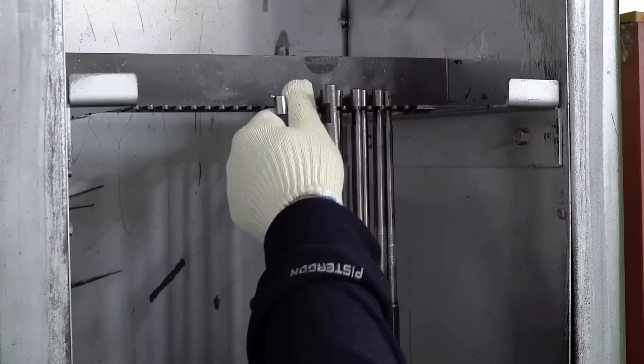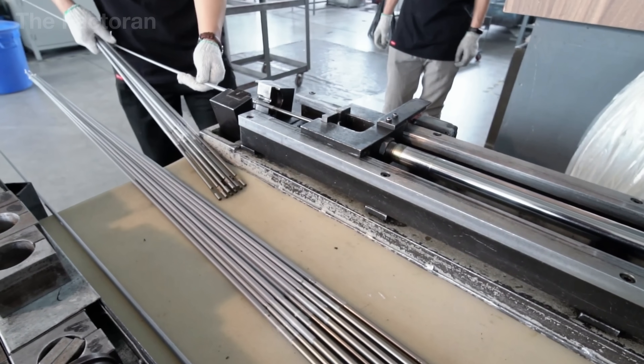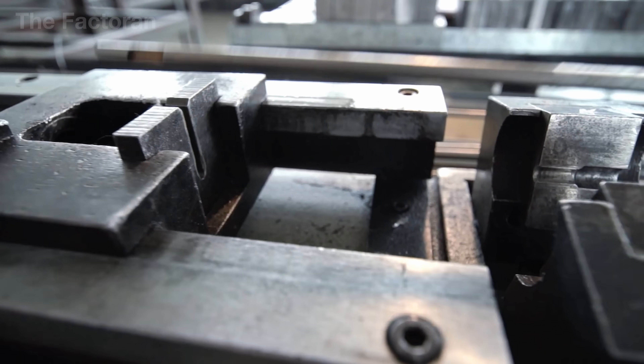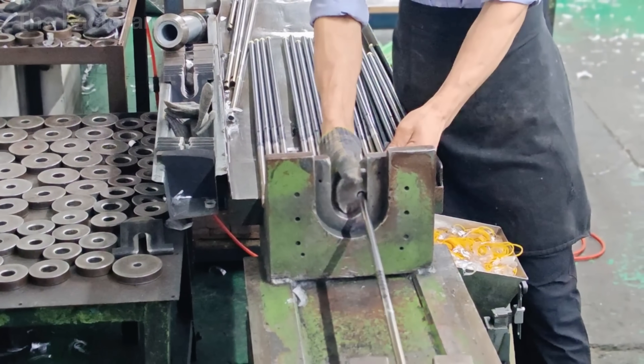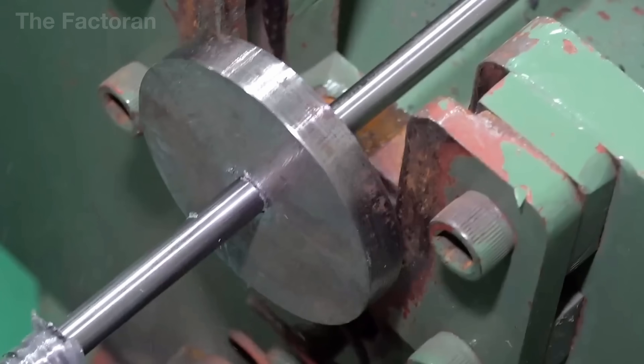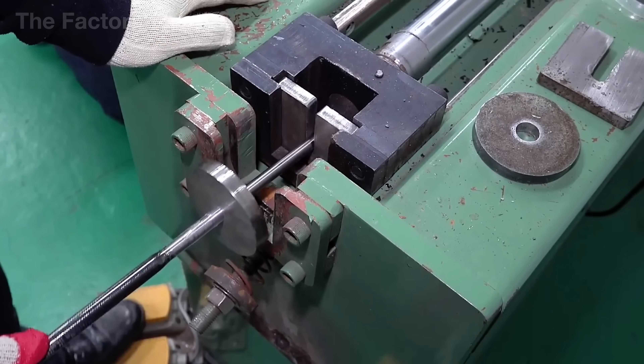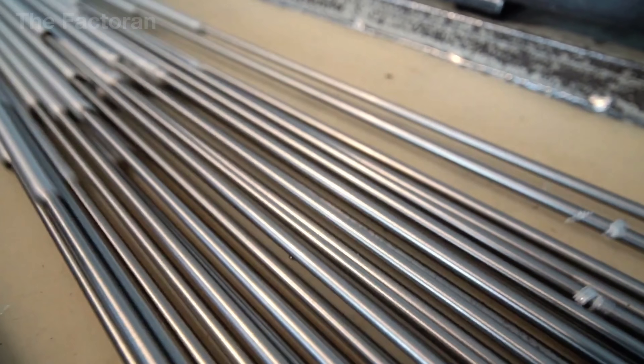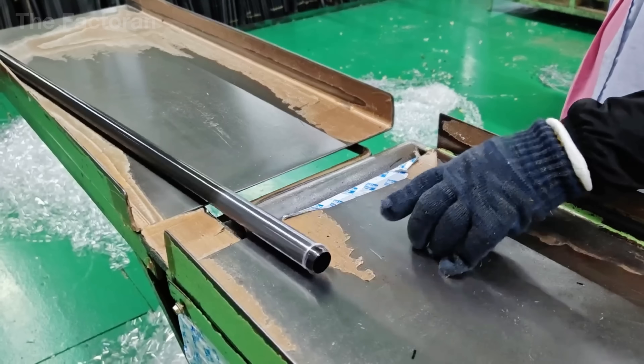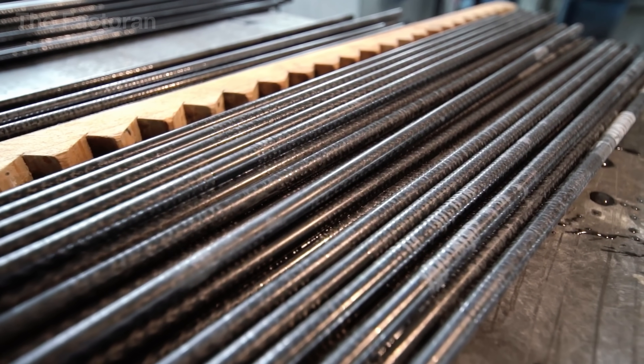When the heating cycle ends and the rod blank begins to cool, the mandrel extraction stage starts. The blank is transferred to a dedicated separation machine where the metal mandrel is clamped firmly, while a pneumatic pulling arm applies a steady and very powerful force to draw the core out of the rod. The pulling force must be strong enough to overcome friction, yet smooth and precisely controlled to avoid deforming the carbon structure. If the earlier heating process was executed correctly, the mandrel will slide out cleanly, leaving a completely hollow rod blank. The technician then performs a quick inspection of straightness and uniformity, relying entirely on trained eyesight and tactile feedback.